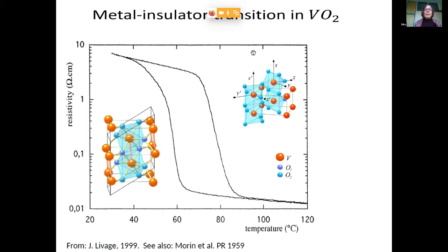Okay, but let's start with the metal insulator transition in vanadium dioxide. So just another way of plotting the same thing that you have already seen. Here is resistivity as a function of temperature. And you see actually the metal insulator transition, which is a first order transition, with a hysteresis curve here, at temperatures slightly above room temperature. And it is accompanied by a structural transition from a monoclinic low temperature phase to a metallic rutile phase.